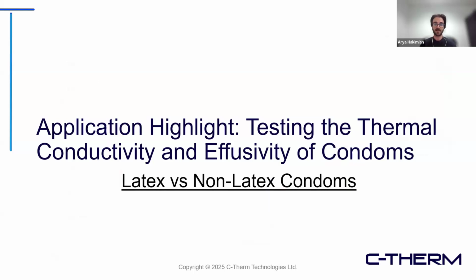All right, so this brings us to some of the actual application data that we collected on the condom samples. In this study, we did a quick assessment looking at the difference between a latex and a non-latex condom, trying to see, are they similar? Are they vastly different? And where do they fall? We did this from a thermal conductivity perspective using the TPS thin films setup for the conductivity measurement, and then from the effusivity side of things, this was done with the MTPS, or modified transient plane source.